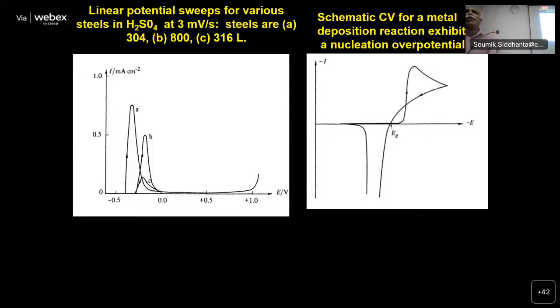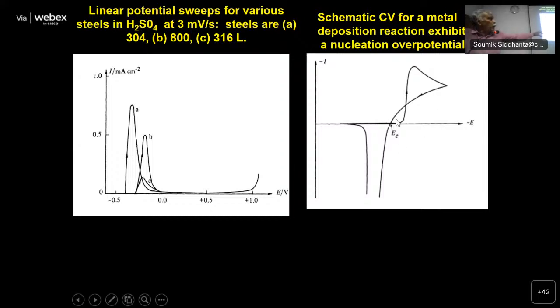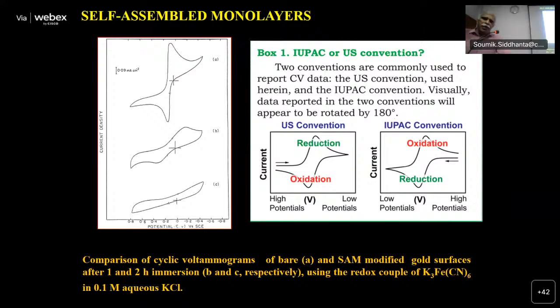There are many other systems where voltammetry can be extremely useful. For example, you can see here, this is one case of stainless steel corrosion, linear sweep voltammetry of stainless steel, passivation. You can see now this current increase and decrease. Decrease means passivation by thick film formation. So all that can be understood by voltammetry. And here you will see some loop formation because there is something called nucleation overpotential. So all that also can be understood by voltammetry. I will not go into the details. In some cases, passivation phenomena can be interesting and can be investigated by voltammetry.